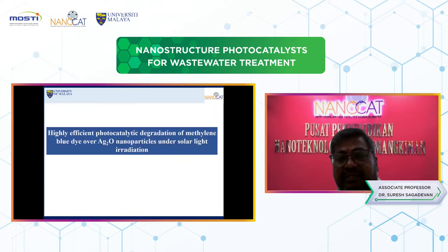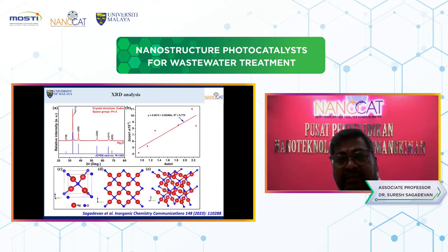Next, we tried the silver oxide nanoparticle for highly efficient photocatalytic degradation. You look at here, this is a crystal structure, which is confirmed as a cubic structure from the X-ray analysis. And the X-ray pattern is very clear and of very high intensity, which means that no impurities are present.